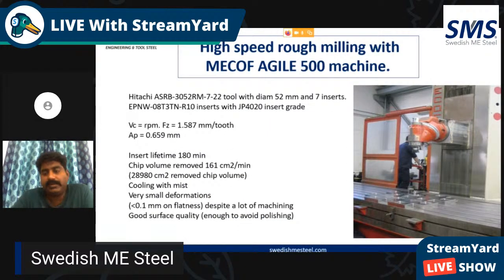So this is a high-speed rough milling where we have tried Toolox. The insert lifetime used to mill this Toolox surface is 180 minutes. The volume of chip removed is 161 cubic centimeters per minute. The total volume is around 30,000 cubic centimeters, and it has only very small deformations even after this extensive machining. So the surface quality of that plate is very good, so there is no need for you to do extra polishing.